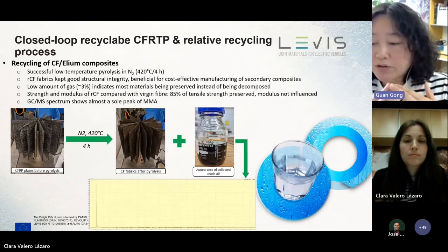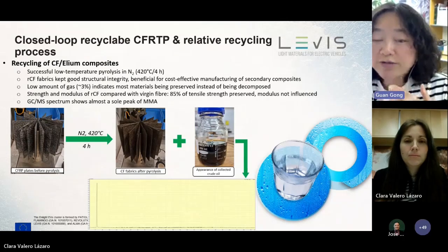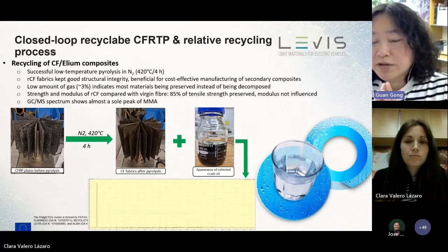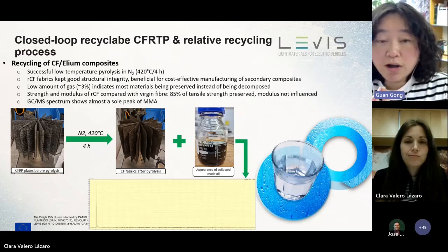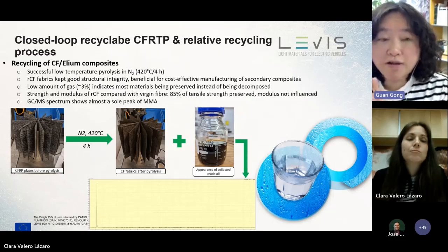And then we also use the single fiber test for a couple of hundreds of fibers to measure the strength and modulus of the recycled carbon fiber. And we found that 85% of the tensile strength of the carbon fiber is preserved and the modulus is almost not influenced. So that is all for my presentation for today.